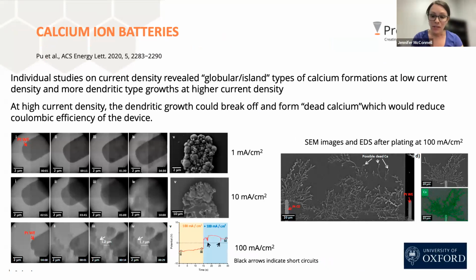Calcium batteries are also a big area of research as an alternative battery material, and you're looking at a similar story here. We're looking at dendrite growth and trying to understand how we can better redissolve the metal during the charge-discharge process. What they're doing here, though, is looking at it as a function of current density. At lower current densities, what does dendrite growth look like? At medium and higher current densities, what does dendrite growth look like?